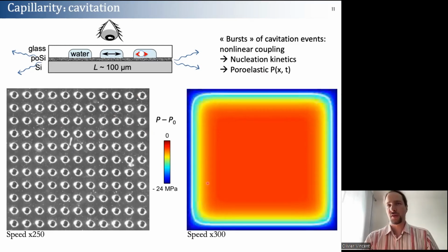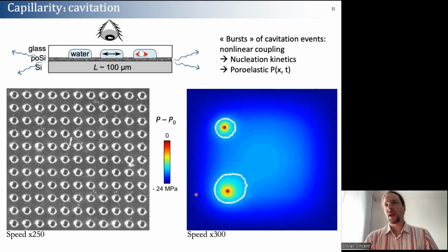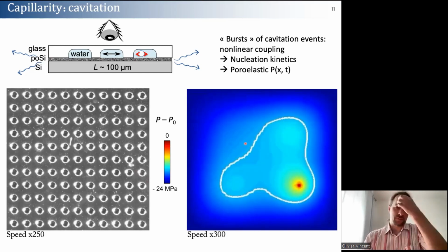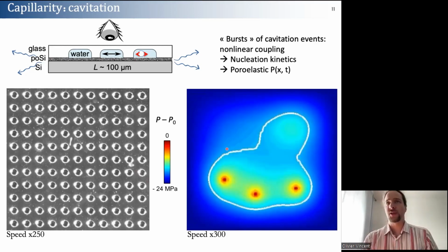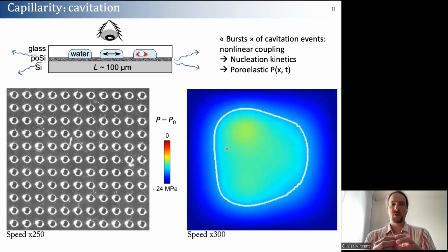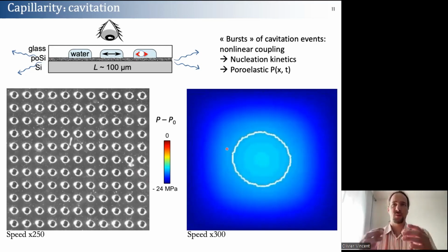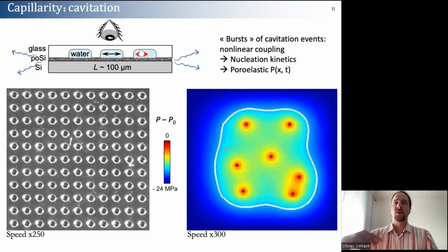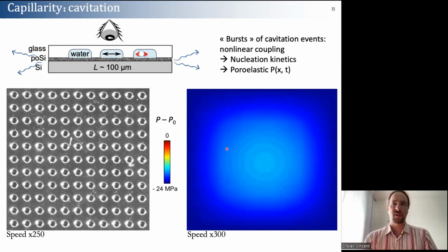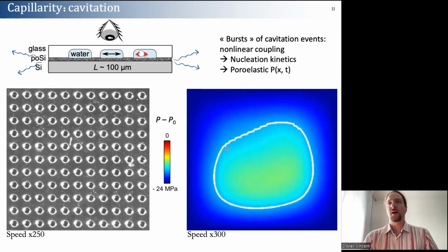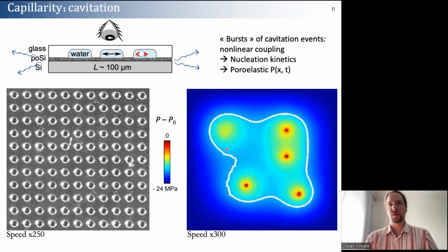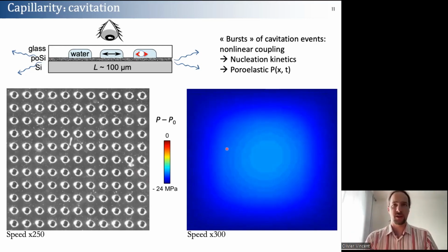And this is a simulation of the dynamics that we simulate in these systems, where each of these red dots is a cavitation event. Once locally the liquid in the microcavities has emptied, the pressure can go back down again, and you generate these cycles of self-organized bursts of cavitation events that are due to this complex evolution of the pressure field over space and time, actually.